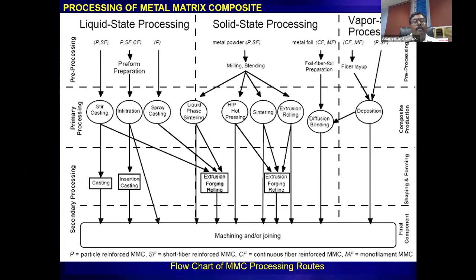So in the primary processing stage, why is it called stir casting? Because we add particles or chopped fiber or short fiber and try to stir it to homogenize this particle or short fiber distribution. So stirring is necessary to have a homogeneous distribution. Once the stirring helps to have a homogeneous distribution of these reinforcements inside the metal, then the conventional casting methodology will help, where you cast it and then try to have secondary machining operations or joining or whatever purpose for which you are making these composites.